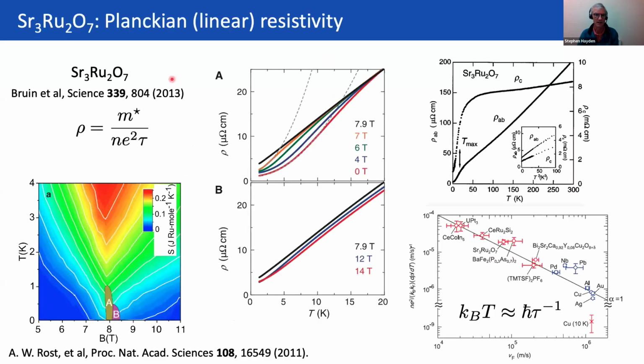This is the bilayer ruthenate material, strontium-3 ruthenium-2 oxygen-7, popularized by Yoshiteru Maeno and Andrew Mackenzie. And of course, this is an entropy diagram derived from the specific heat, showing that there's something like a quantum critical point appearing as you change the magnetic field. Here we've got the resistivity plotted for different magnetic fields, and one can see that at high fields, at the point where you get to this thing that looks like a quantum critical point and beyond, you get a very nice linear resistivity. And at low fields, it's more curved with temperature. So the linear part is strongest in the right-hand side of this phase diagram.